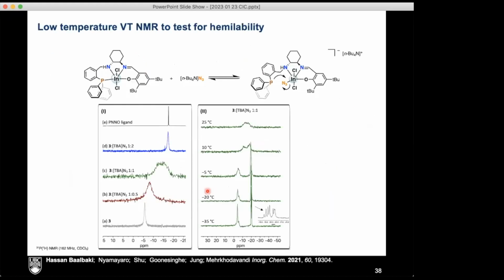So let's think about what it is that the indium is doing. So remember that I said that we need tetrabutylammonium azide as the nucleophile to get this reaction to work. And so let's say that the first hypothesis is that we need to have the azide coordinate to the metal. Is this something that's happening in this system? And in fact, it is. So when tetrabutylammonium azide is added to the system, in the case of the indium, I said earlier that the phosphine was coordinated. And in this case, the azide seems to be helping pop that phosphine off. The azide can coordinate, and we can see that as we add more azide to this. We can see it pop off.